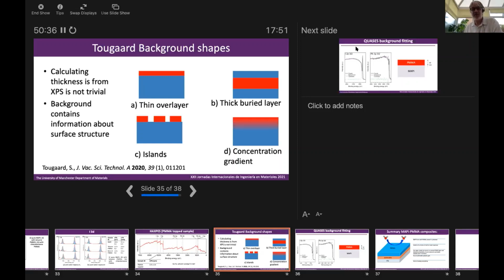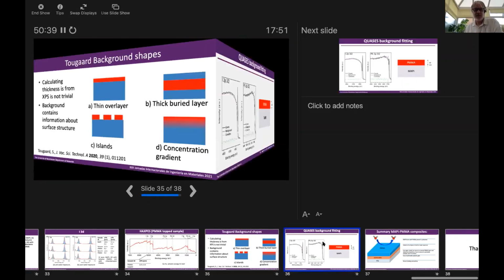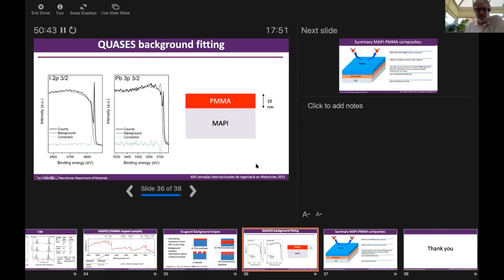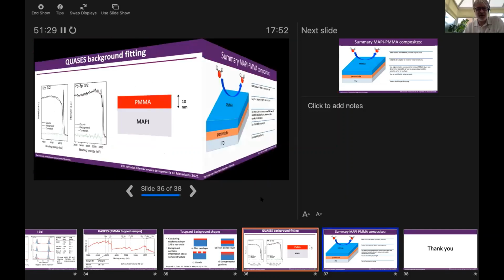And XPS actually allows you to do that. There was some work done by a group in Sweden led by Sven Tougaard, which showed that if you fit the background, this can give you information about the structure of the overlayer. In our case, we found a very good fit to both the lead 3p and the iodine 2p background. We're not so much worried about the actual photoelectron peak. We're interested in what happens to the photoelectrons as they come out, because it's the scattering of these photoelectrons which gives rise to the background. Depending on the structure of the overlayer, this will cause different background shapes. We find for these two that a continuous overlayer, a thin film of around 10 nanometers, fits this data very well. This is a development which I think you're going to see more and more of in the XPS literature in the next few years.